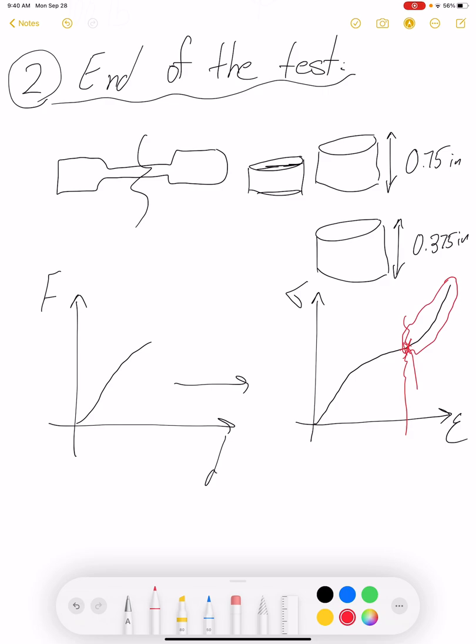Here let's call this ultimate compression, this one would be the modulus. Experimental results have shown that the tensile modulus and compression modulus have to be theoretically the same. Because for tension and compression we are using different specimens that have been manufactured differently, we don't expect it to be identical but they should be close.